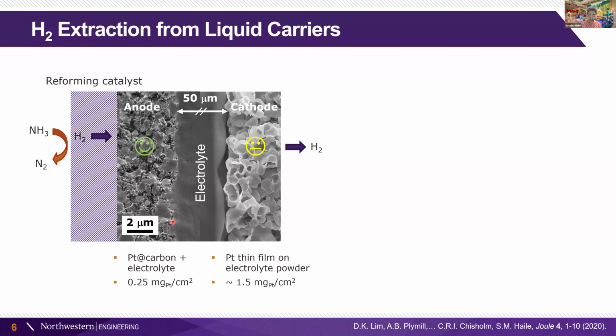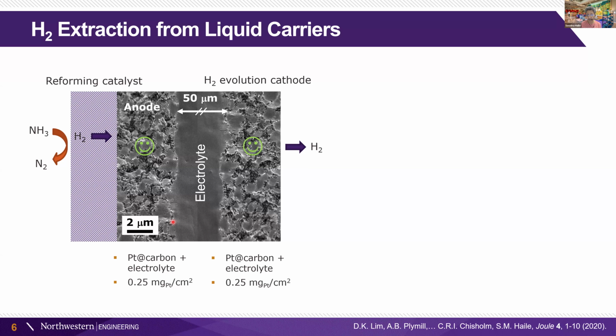So the advantage here is that we replace that difficult cathode material with our hydrogen evolution cathode, which allows us to lower the platinum loading and design the electrode structure in a way that provides greater stability. So these devices operate much better in terms of the long-term degradation than our fuel cells.